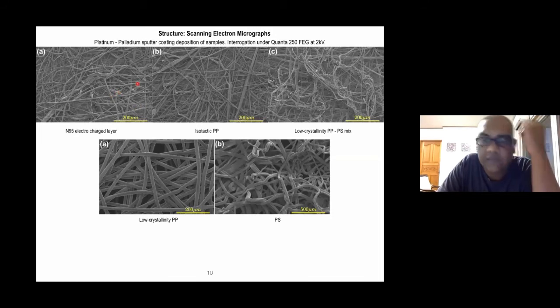I was trying to study the structure of these electrocharged filter polymer fabrics. I'm showing you the scanning electron micrographs for these. The one on the top left corner is from a commercial N95 electrocharged fabric, an N95 respirator from 3M. The one in the middle is from isotactic polypropylene, and the one on the right is from the polypropylene polystyrene mix. The isotactic polypropylene seems to give me more straight nanofibers compared to the N95 layer, which seems to be more tortuous. But I found that 80% polypropylene and 20% polystyrene gave me this kind of tortuosity, which comes close to what we observe for the N95.